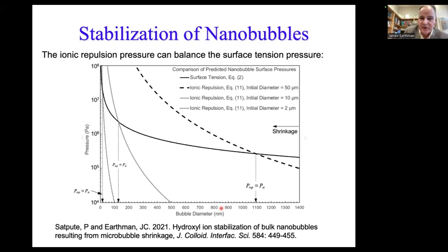The largest of which should be about 1,100 nanometers, because that corresponds to starting out with a 50 micrometer microbubble. If the microbubble is larger than this, it won't shrink. Surface tension pressure is not high enough. But if it's this size or smaller, it will shrink to the nanoscale. And according to our theory, it should stop shrinking because of the repulsion pressure at about 1,100 nanometers.